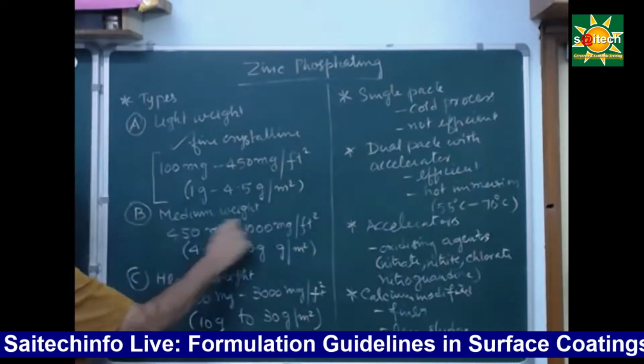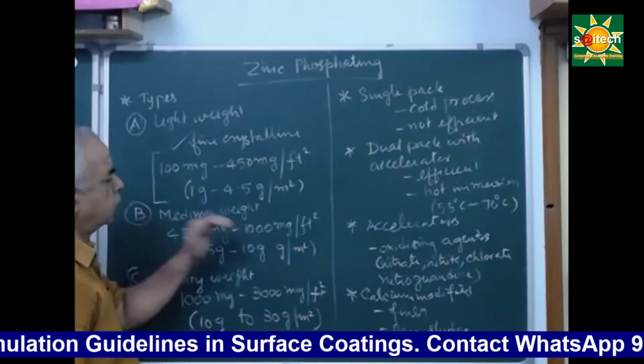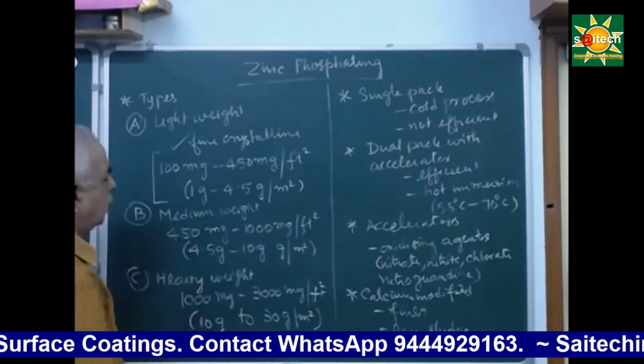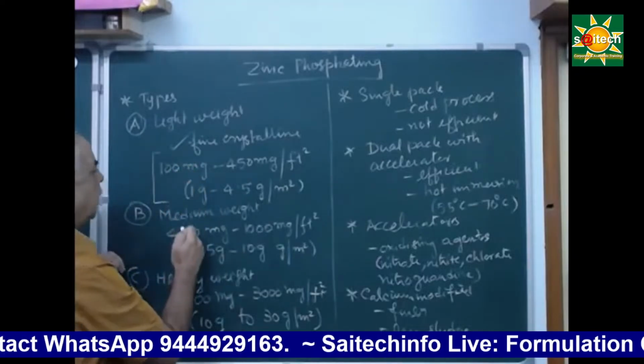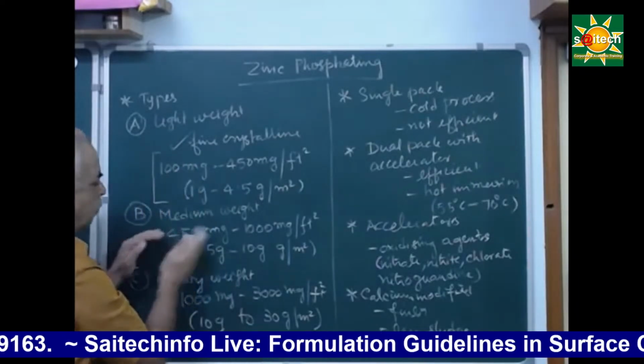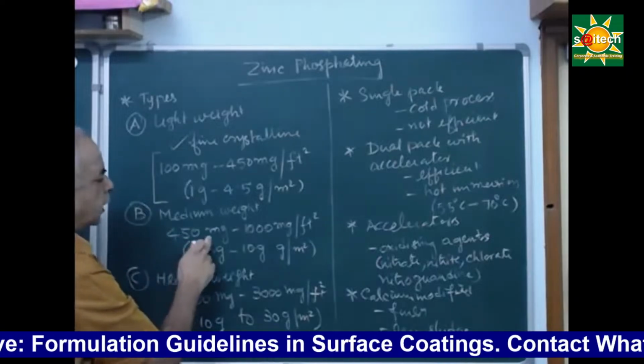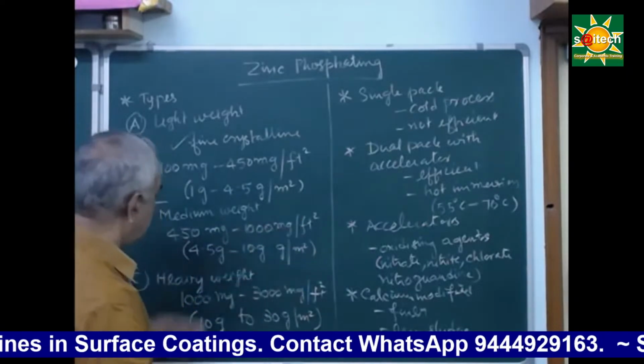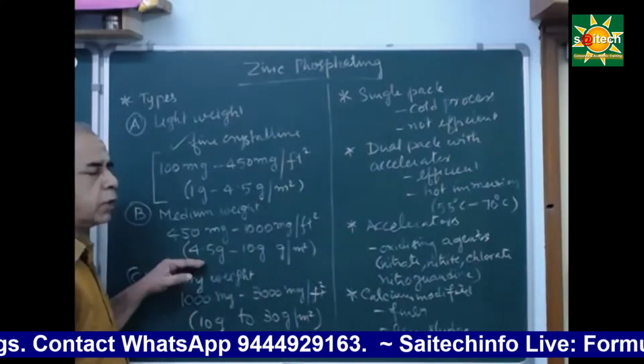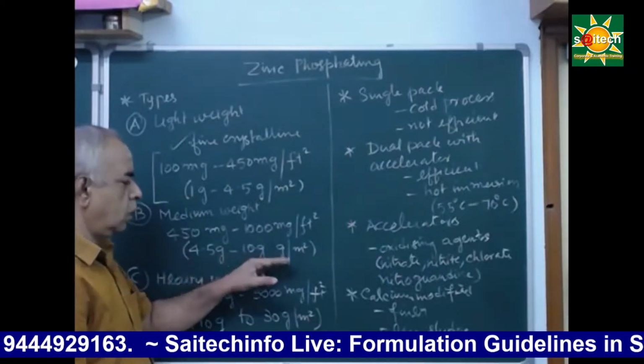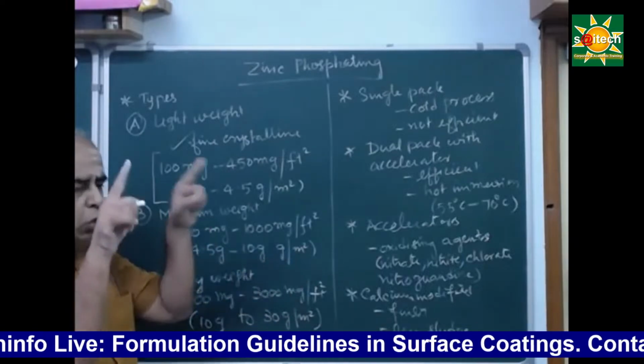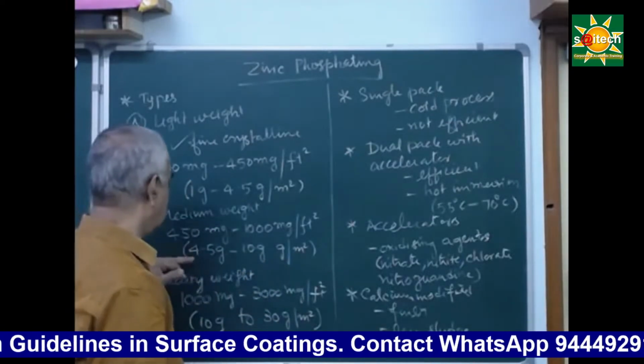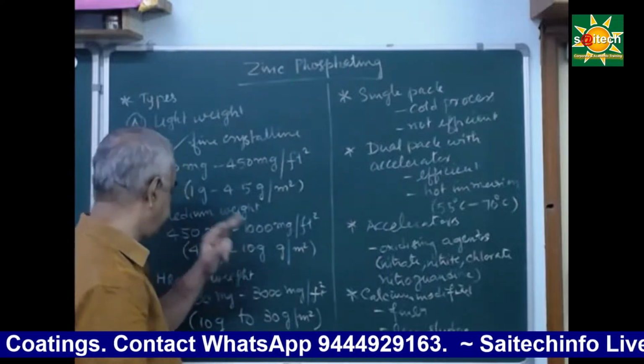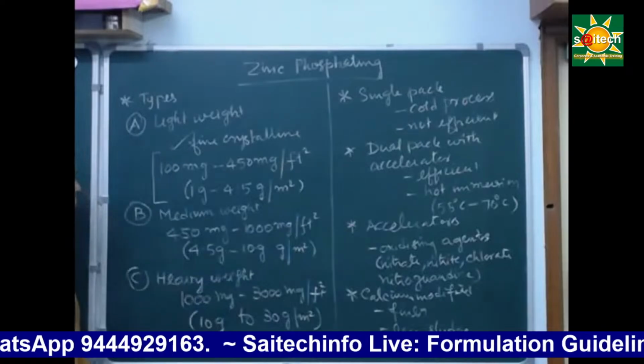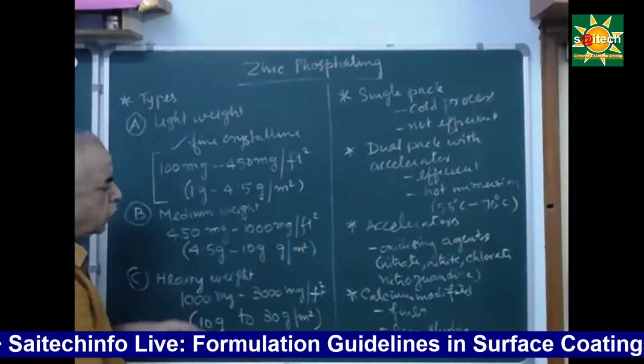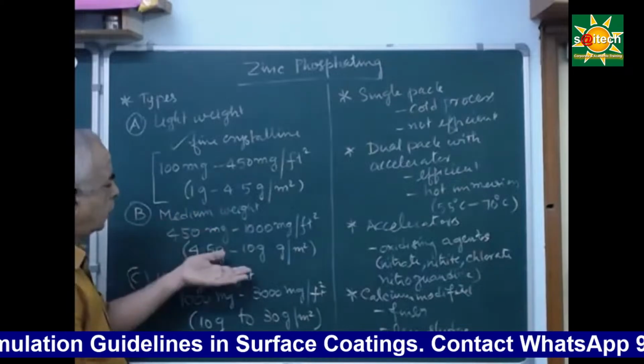And then medium weight is 450 milligram to 1000 milligram per square feet. So here it is somewhat heavier than the lightweight. Of course, it is a medium. So 450 milligram to 1000 milligram per square feet, and in terms of gram, 4.5 gram to 10 gram per square meter. When you take a 1 square meter component, it will coat 4.5 gram to 10 gram. So this is known as medium weight, and these two are applicable for coating industries, where after treatment of